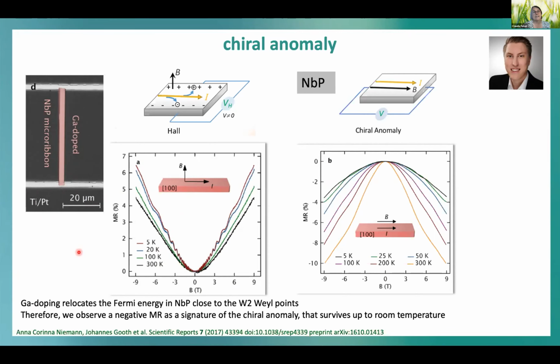And here we tried it with niobium phosphide, because this was our most favorite material. We were more or less lucky, because when Johannes got this microribbon, this compound was simply autodoped by gallium via the focused ion beam tip, and this autodoped the material to have the Weyl points at the Fermi energy.